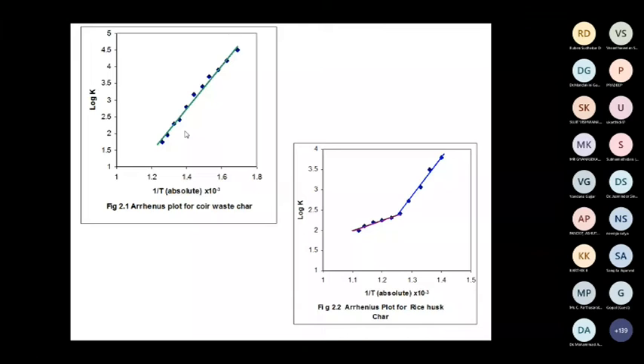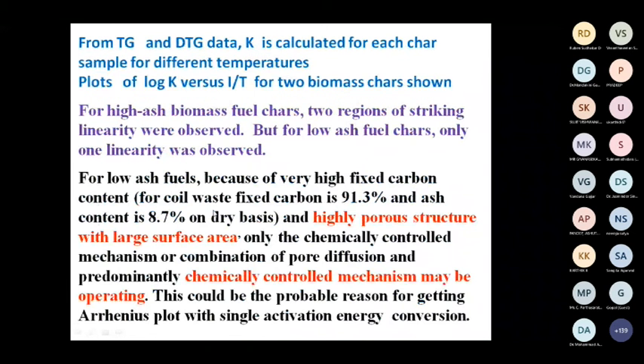Okay, sorry for that. For coir waste char you have one linearity, whereas for high ash rice you have two regions of linearity. That's what I want to explain now. The reason being, for low ash fuels you have very high fixed carbon, about 91% in the char. Char is highly porous, as I already explained. Because of the highly porous structure with a large surface area, only a chemically controlled mechanism may be operating for low ash char. That is why we have one linearity.